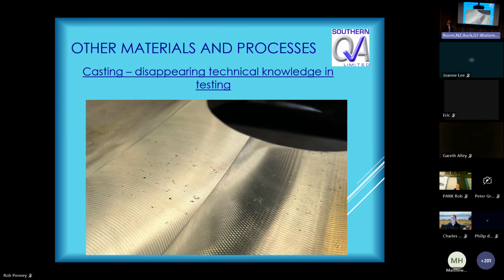And we had to x-ray the welds. And when we x-rayed the welds, we found all the shrinkage in the adjacent parent metal. And when we had a look, about 70% of the area of this ring of casting was like this. It was completely non-compliant. Not only is the knowledge for how to do the casting disappearing, so is the knowledge for how to do the testing.